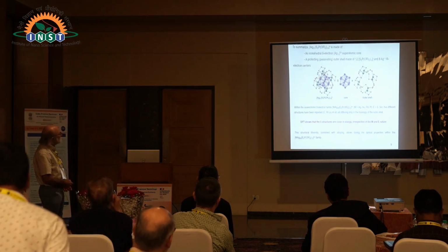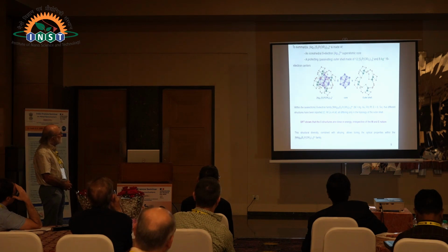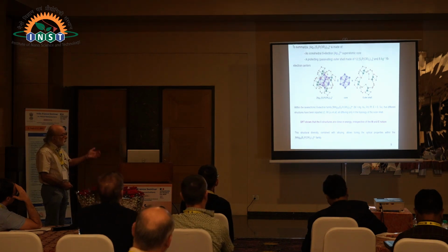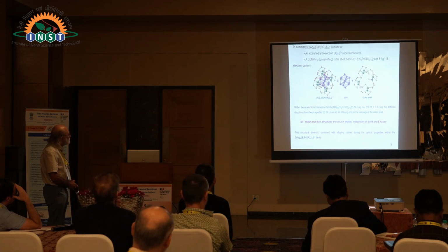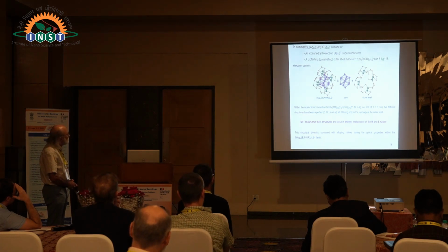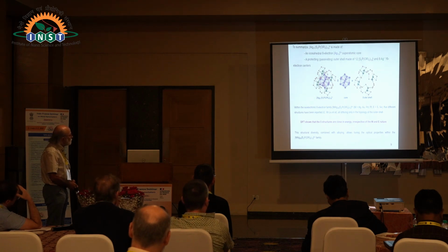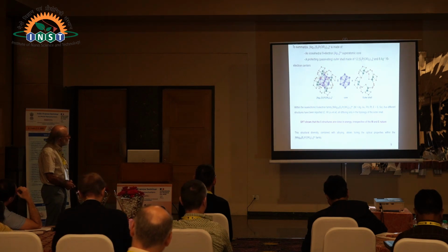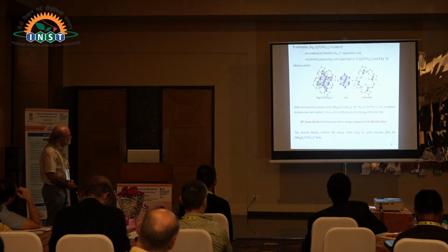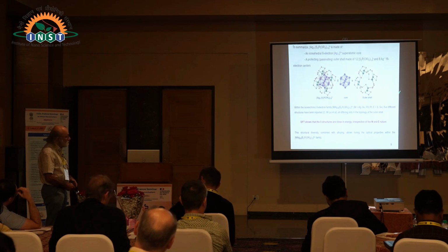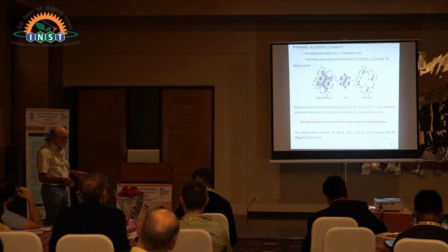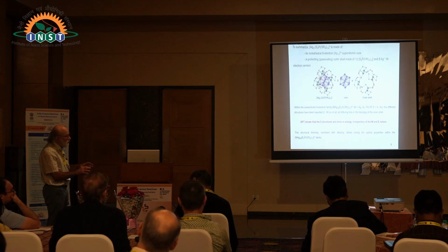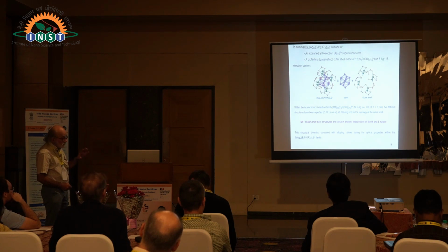So just to summarize, this compound can be divided into two parts. The real superatomic part, so to speak, which is the core, silver 13 formally 5+, and the protecting shell, which is made of 12 dithiophosphate ligands and 8 silver 1. If you look at the green atoms, silver 1 in the +1 oxidation state, they are in trigonal planar coordination. So they are happy. They are happy as they are. They are stable locally, a planar 16-electron center. They are not going to seek additional bonding.